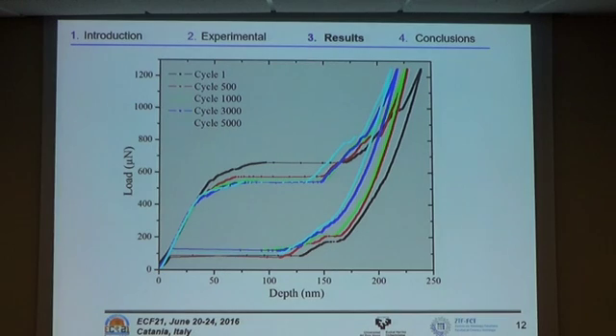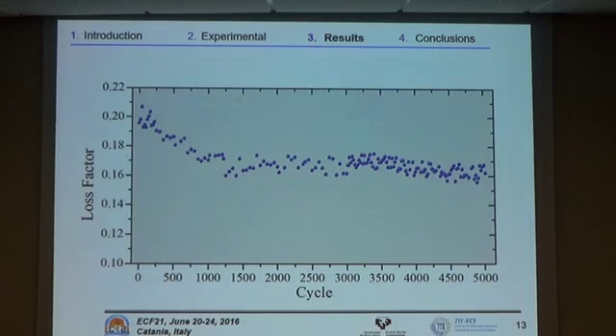Of course, 5,000 cycles in fatigue studies is not too much, but you have to keep in mind that we are in a nanoindentor, it's not a fatigue machine. And we also work in load mode. I would say that if we work in displacement mode, and we introduce a strain of 1% or 2%, we could go to a much larger number of cycles. And about damping capacity, which is in fact the same type of data, after the initial training we get a plateau in the loss factor value, which is quite reproducible after. And this is repeated not only for this pillar but for other pillars as well.